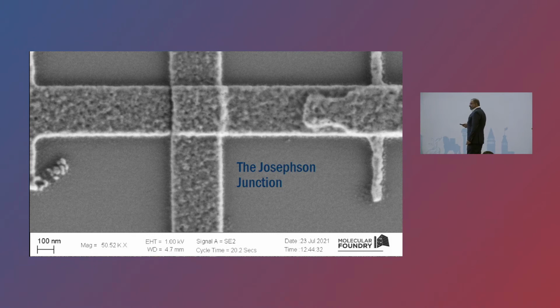Then there's the junction. The junction inside also has dielectric materials. In this case, we're looking at aluminum, aluminum oxide, aluminum. And if you think about the material inside, perhaps one of the reasons we have not been troubled by this yet is that it's really small. These are sub-100 nanometer junctions. If you do the estimation of at what level of coherence we will be plagued by the Josephson junction, we're starting to get there. As you start to remove the oxide from the outer surfaces, the junction starts to matter. And if we have, let's say, a few hundred microseconds of coherence time today, to exceed some milliseconds, we will have to pay attention to the Josephson junction inside.